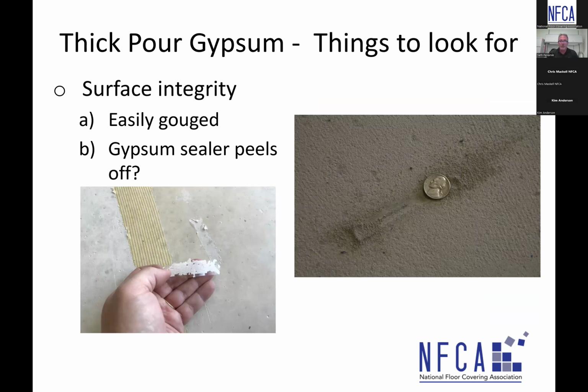Is the surface easily gouged? Does the sealer peel right off, like you're seeing here? When you're doing a mat bond test, are we just peeling the surface right off with no effort at all? You can see in the picture here the remnants of a 3311 mat bond test. You can see the adhesive right in the middle of the picture, and the adhesive was basically combed out a little wider than the size of the floor covering. To the left is where they peeled the floor covering off. And to the right, you can see that little strip of sealer that's peeling right off, and the gentleman is actually holding it in his hand.